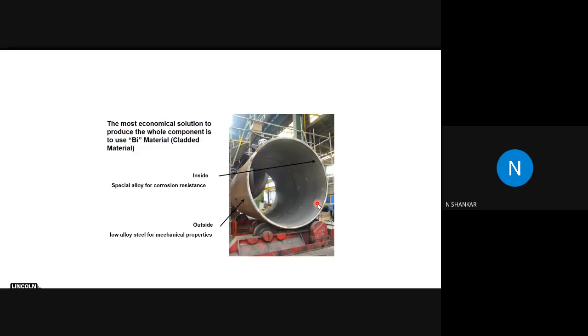So what people have started doing is they have a base material of one composition, and on the inside, where corrosion resistance is required, they overlay it with a different material. That's called cladding. It's a bi-material cladding. From the outside you'll have low alloy steel, and from the inside a special corrosion resistant alloy. The mechanical properties are taken care of by the outside one.